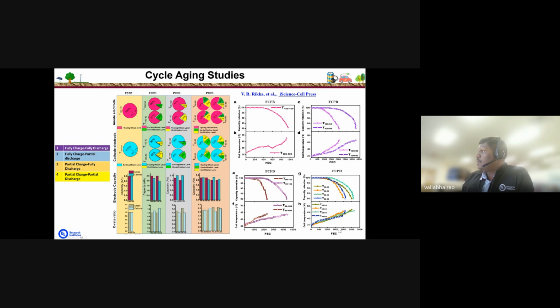So for the full charge and full discharge test condition, the cycle life was limited to only 900 cycles, whereas in other test conditions the cycle life number was increased tremendously. Compared with full charge, full discharge, it's almost 2 times for full charge, partial discharge, whereas it is almost 3 to 4 times in the case of partial charge with the full discharge. Interestingly, the partial charge and partial discharge cycle life was in between the full charge, partial discharge, and the partial charge and full discharge.